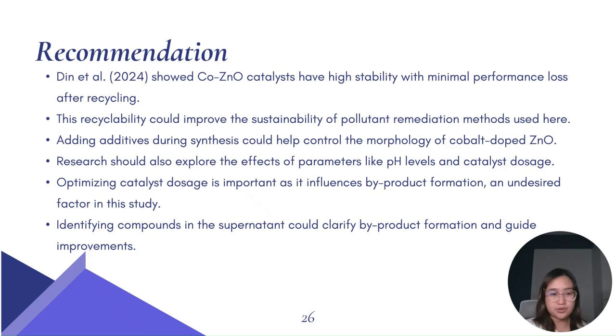For recommendations for further studies, in a study by Din et al., they showed that Co-ZnO photocatalysts have high stability with minimal performance loss after recycling. This recyclability could improve the sustainability of pollutant remediation methods used here. Also, adding additives during synthesis could help control the morphology of cobalt-doped zinc oxide, especially with higher concentrations of cobalt doping. Research should also explore the effects of parameters like pH levels and catalyst dosage. Optimizing catalyst dosage is important as it influences byproduct formation, an undesired factor in this study. Also, identifying compounds in the supernatant could clarify byproduct formation and guide improvements. This can be done, for example, by the use of GC-MS.